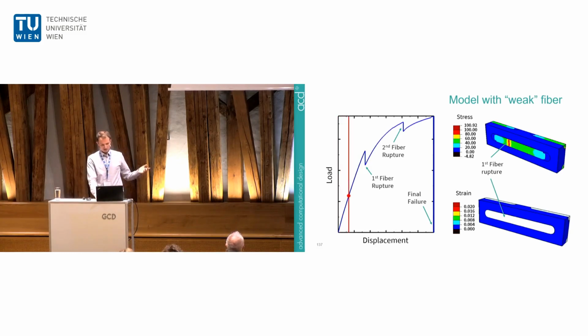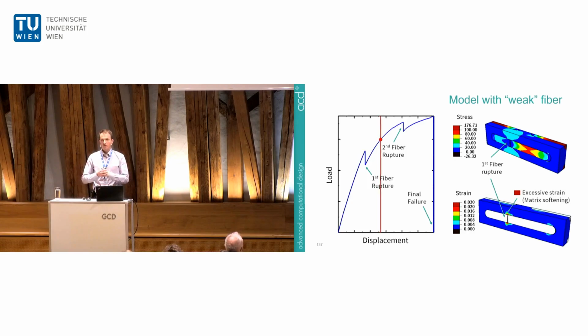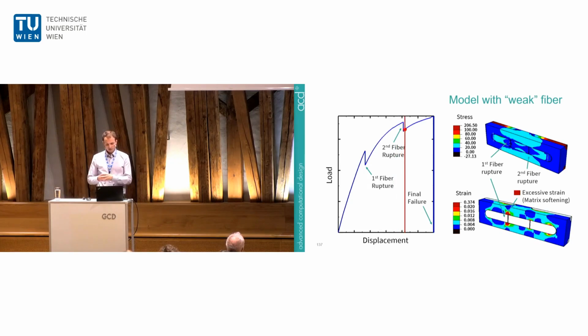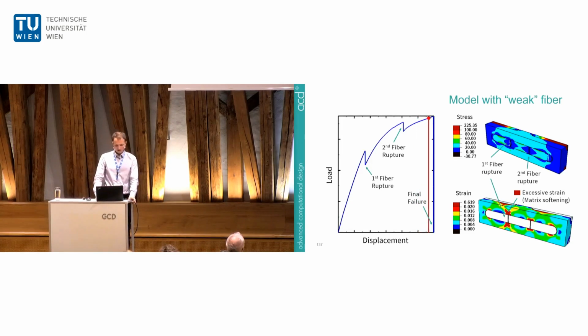So a first crack is initiated in the fiber, resulting in this load drop, but the surrounding matrix is still capable of distributing all the forces, which allows the biocomposite to bear even more stress. But starting from this fiber crack, the matrix gets slowly damaged, and in parallel a second fiber crack is growing, and suddenly the whole composite fails, where various failure mechanisms grow together.